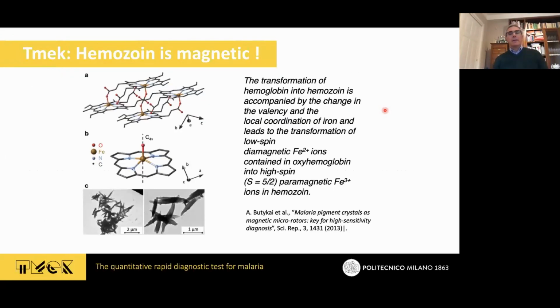Now, in any case, everything is based on the hemozoin properties, which is the fact that these hemozoin crystals are magnetic. What's the reason for this magnetism? The reason is quite simple. This is the structure of the typical dimer, which is the basic building block of the hemozoin. And what is happening is that you have the porphyrin-like structure here with an iron at the center. And typically, in the hemoglobin, the oxidation state is 2+.